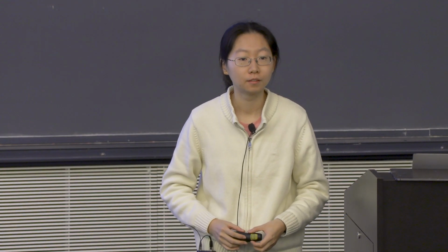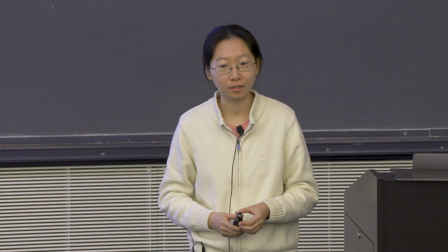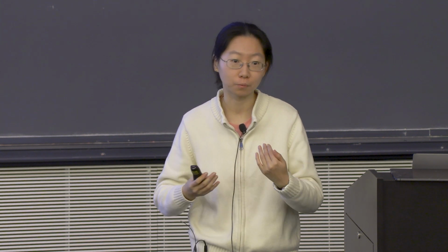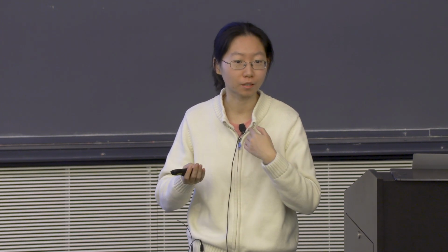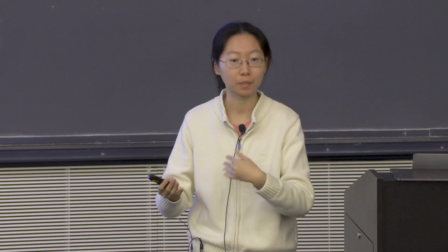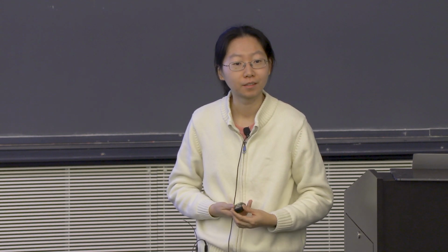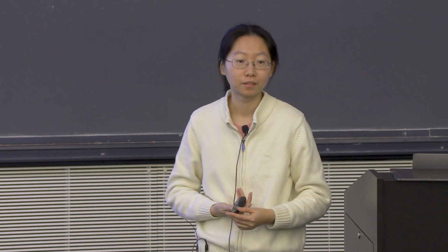Hi. I had a question about twisting monolayer boron nitride. I know this is a very hard task. What method did you use to twist monolayer boron nitride? Yeah, it's actually not as hard as people think. It's the same idea as twisting graphene. You basically use a thicker boron nitride, and then you engage a monolayer BN. You pick it up, and by just picking it up, you can tear it, and then you engage to pick another one. So you tear the layer during the pickup, you stop halfway, tear it up, and rotate the bottom.